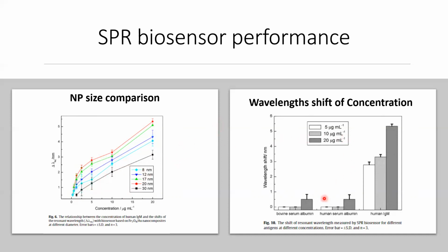And on the right side, we see a test to make sure that this biosensor effectively detects the presence of this specific antibody. They tested with 2 other antigens: bovine serum albumin and human serum albumin. And as you can see, with these other antigens, it didn't show a significant response.